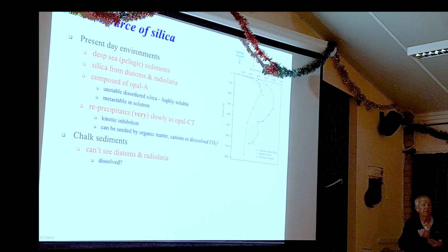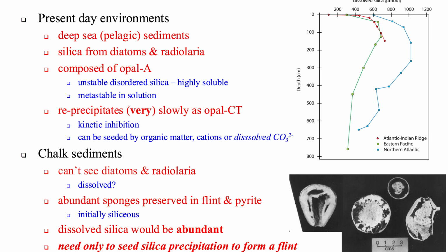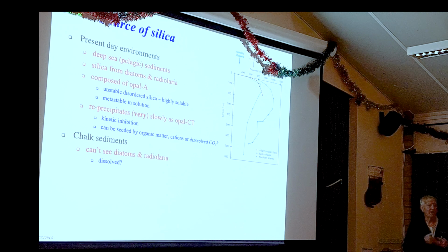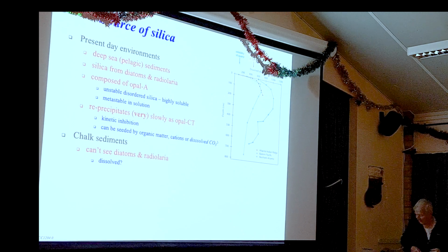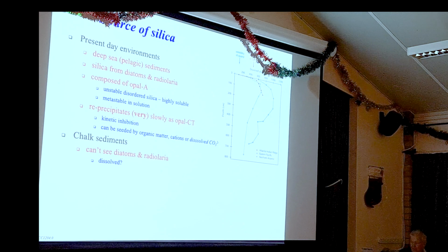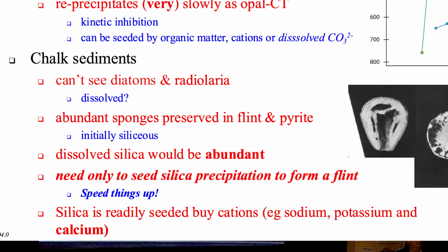And then when it's in solution, we have silica solution. The solution tries to precipitate out either as quartz or as opal CT lepospheres. The problem is it can't. It needs something in there to speed the process up. Otherwise it just sits in metastable solution for millions and millions of years. So we need something to seed. Now we do know that opal A exists in the chalk, or existed in the chalk, because diatoms and radiolaria microfossils are composed of opal A, but we don't find any of those left in the chalk. They've clearly dissolved.